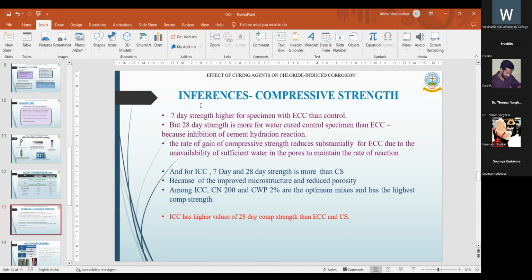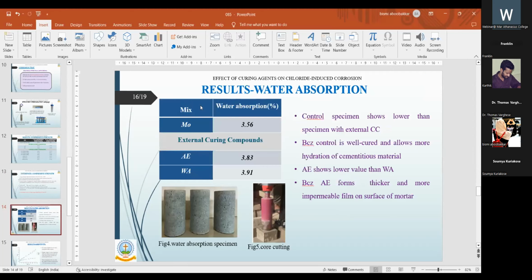And among integral curing compounds, CN200 and CWP 2% are the optimum percentage and have the highest compressive strength. Comparing the external and integral curing compounds, ICC has higher compressive strength than ECC and the control specimen.